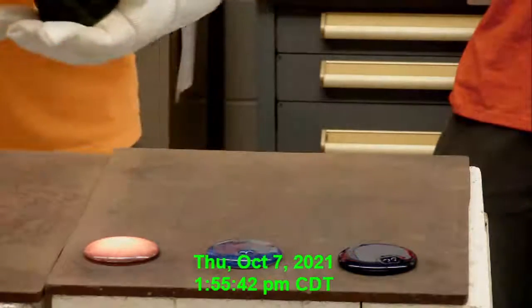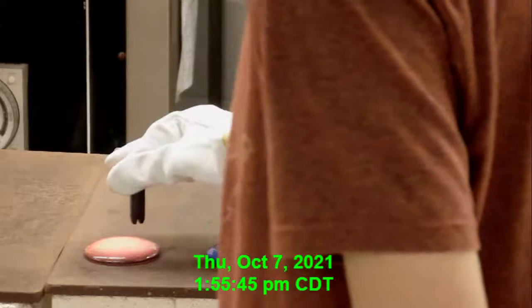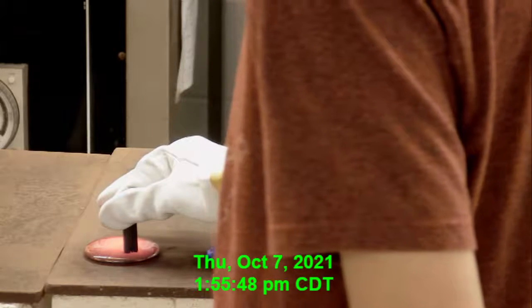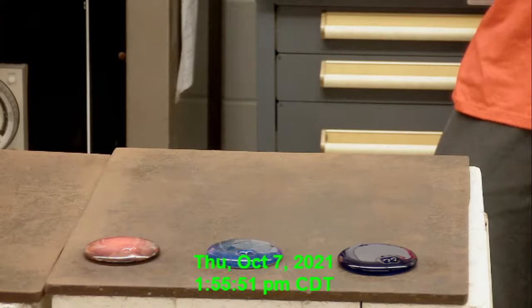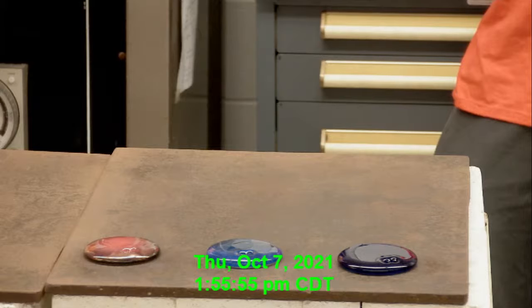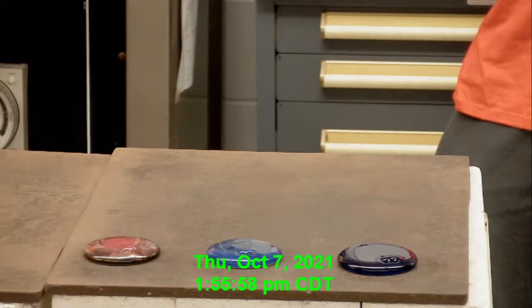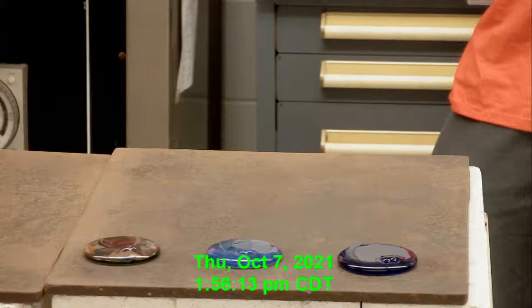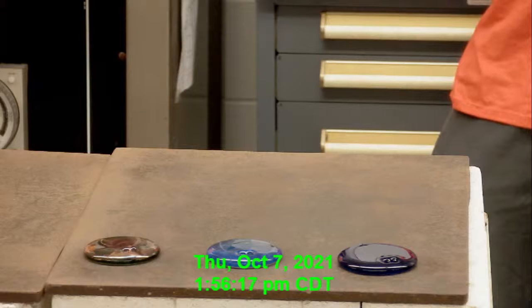Okay, I think it's good. And one of the things that we often see with the copper glass is the flame has some excess carbon monoxide, and I can see it already forming there. Some of the copper gets reduced in the surface layer of the glass, and the cool thing about that is there will be a copper mirror-like appearance, and you'll be able to see that kind of banding on the surface of the glass. I'll clean up these crucibles later, so we could, in theory, chip off that glass so it's not like a bee stinger that's going to get you.